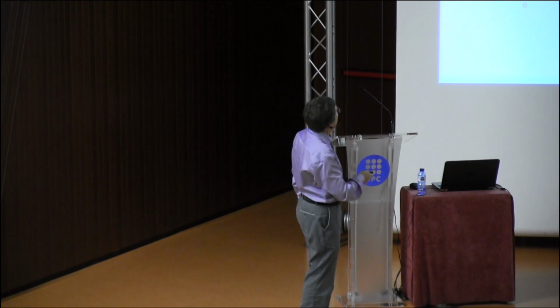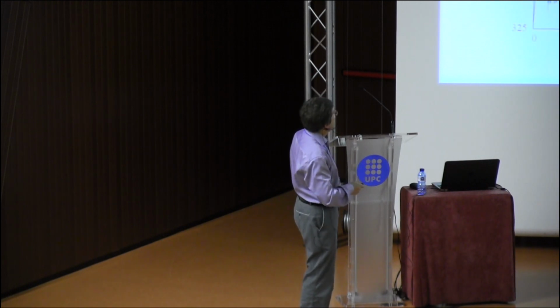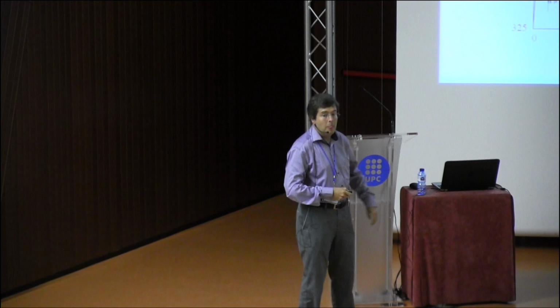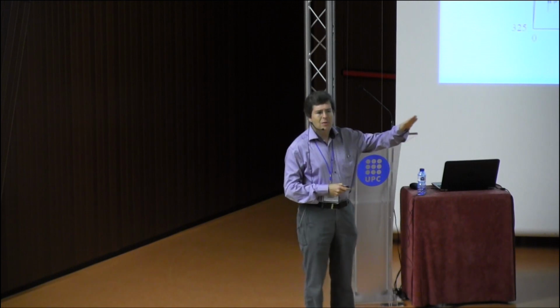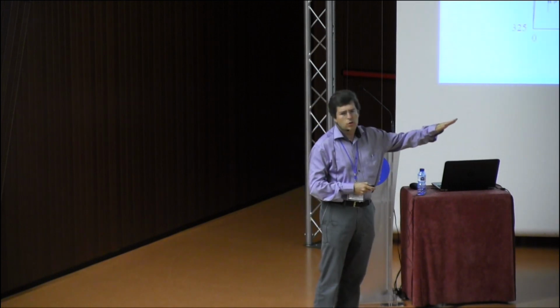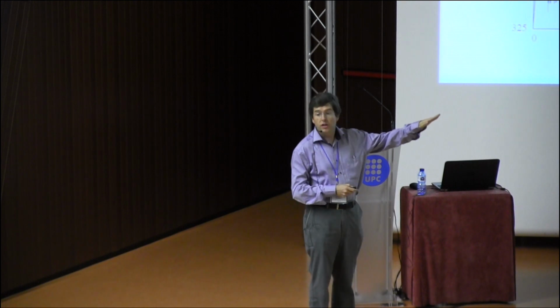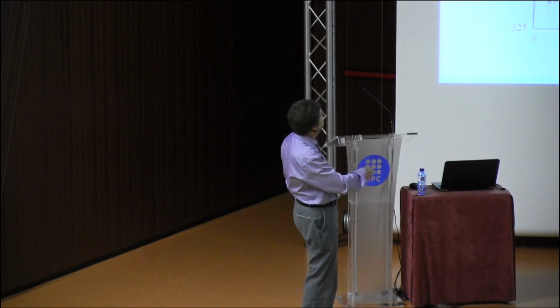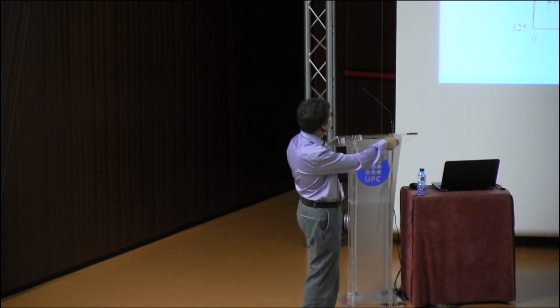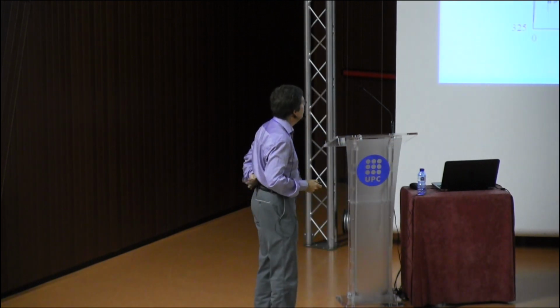But if you are nasty and align the elements parallel to the localization band, because you can predict the orientation of the band, then this is a nightmare - what you get is this very strong curve. It has nothing to do with the experimental curve, in fact.